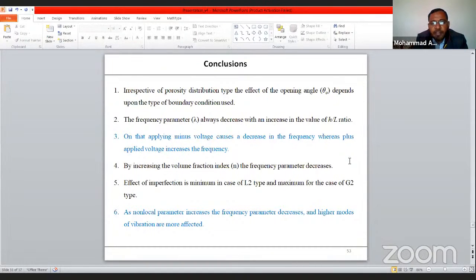The effect of imperfection is minimum in case of L2 type and maximum for the G2 type geometric imperfection. As the non-local parameter increases, the frequency parameter decreases, and the effect of this non-local parameter is highest for the higher modes. Like as I have discussed, it was around 73% for the fifth mode of the vibration.